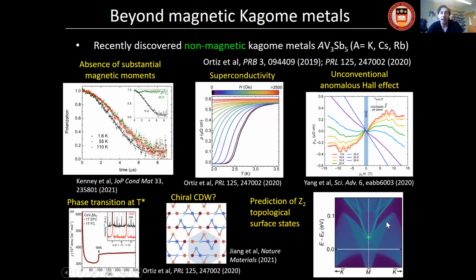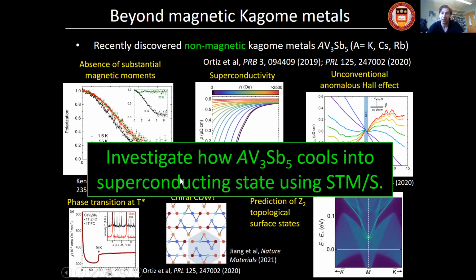And theory further predicted topological surface states. So this would make all these correlated phenomena that I talked about, or at least this charge density wave state, a little more interesting. And finally, what really gathered the interest of the community was the discovery of superconductivity. So in cesium-based vanadium antimony, the superconducting TC was at about 2.5 to 3 Kelvin. So there's a lot of interesting phenomena that were discovered months after the synthesis of this system.